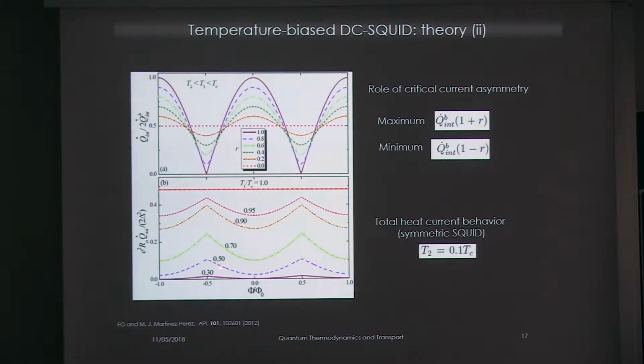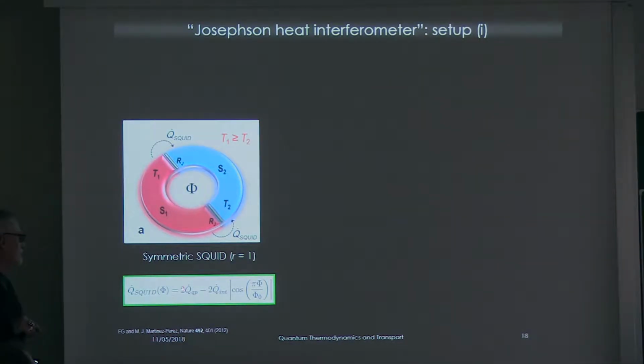And then of course you increase by increasing the temperature. If you block one of the two and you increase the temperature of the other, you can have very large oscillation. In the end they start to decrease because one of the two gaps starts to become smaller, and eventually, when we reach the critical temperature of the one, it is no more phase sensitive. Okay, so this is what to keep in mind.